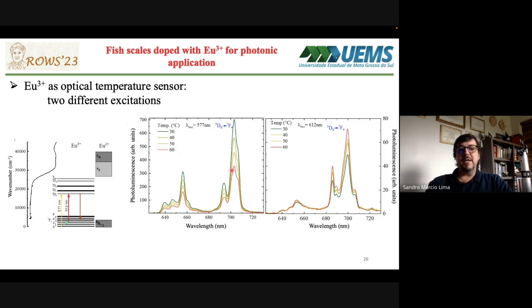As expected, by increasing the temperature, we observed a considerable decrease in the photoluminescence intensity, mainly due to the loss in the population of 7F0 that I showed before. On the other hand, the photoluminescence registered with the excitation at 612 nanometers increases. The signal increases here when the temperature goes from 30 to 60 Celsius degrees, reinforcing what was theoretically predicted.